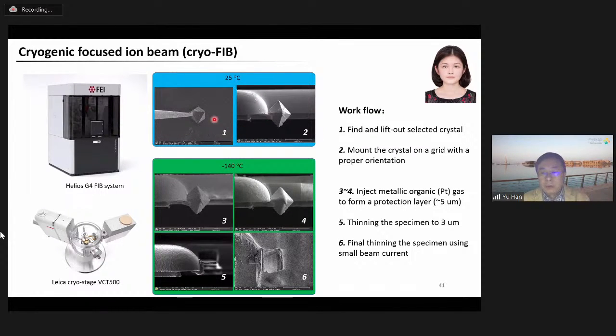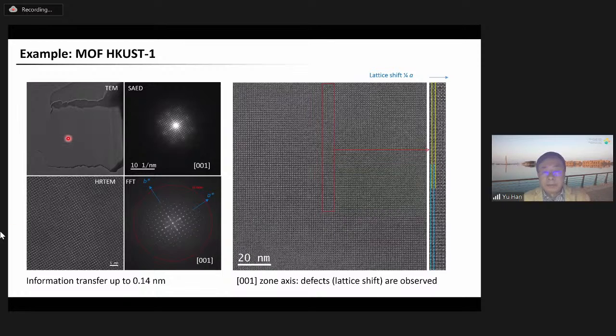Okay, so this is a workflow that shows how the crystals were selected and mounted onto a TEM grid and protected, and then finally cut and thinned into a very, very thin slice for TEM imaging. So the slice, you see, this is the slice prepared by cryo-FIB. The slice prepared by cryo-FIB is thin enough for high-resolution imaging. As you can see here, very nice electron diffraction patterns, and the image obtained can give a resolution as high as 1.4 angstrom. This indicates that the MOF structure was well preserved during the specimen preparation process.